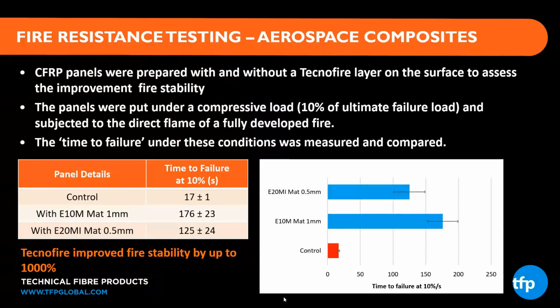So let's take a look at what was actually investigated during this project. So CFRP panels were prepared using vacuum-assisted RTM with an epoxy resin with and without a Tecnofire layer on the surface to assess their potential improvement in fire stability. And I think it's fairly well known that CFRP composites can retain a reasonable proportion of their tensile properties at elevated temperatures due to the stiffness of the fiber, but they tend to fail under compression very, very rapidly once the resin hits its glass transition temperature. Again, as Scott alluded to, with a T critical in the Aachen study.